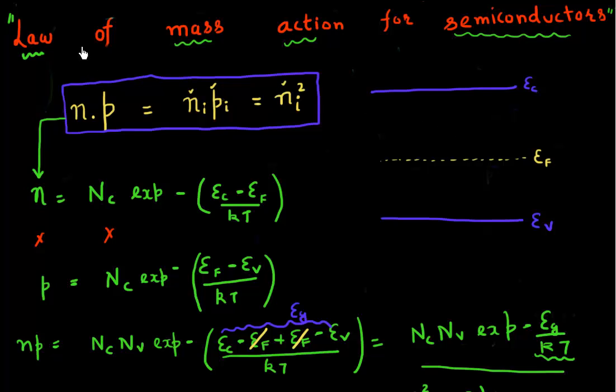Now what happens if I move this Fermi energy? Let me move this closer to the conduction band. What this expression is telling me is that if I move this energy closer to my conduction band, then my Ec minus Ef decreases. And correspondingly, this distance of Fermi energy from the valence band increases. So this term decreases.